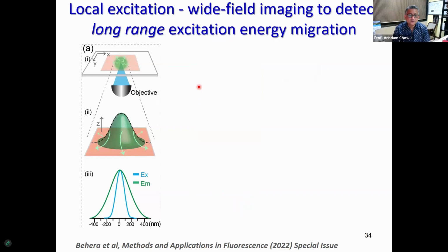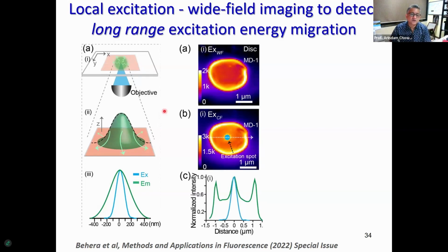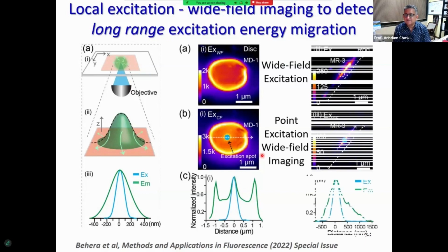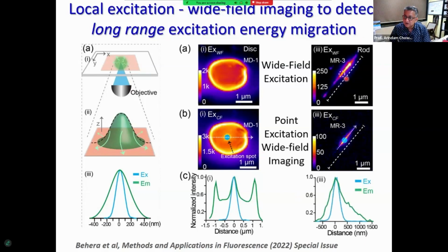We locally excite it. Once we locally excite it, we can use filters to look at the excitation profile. And then we look at the emission, which is shown in the green, using another filter. On the top here is shown a wide field image where everything is excited together. In the bottom here in the blue, this is where the excitation point is. When we look through a camera or through an eyepiece of a microscope, we see the entire crystal. Exact same thing happens when it comes to the rods. You can see I can locally excite it. This is the entire crystal excited with the light. There's a defect in this zone. But when I locally excite it over here in this bottom panel on the right, you again start seeing emission coming from beyond the local excitation zone.